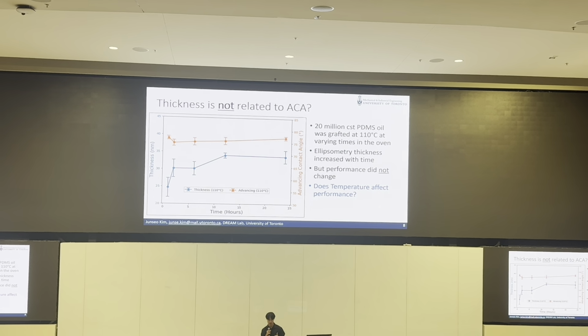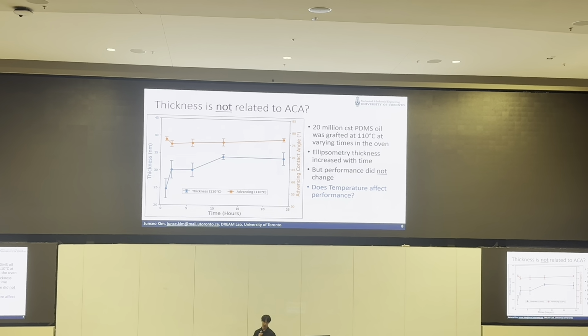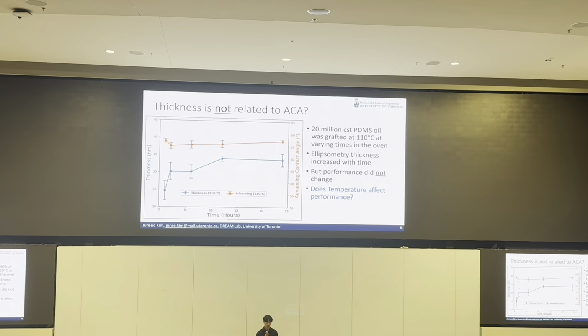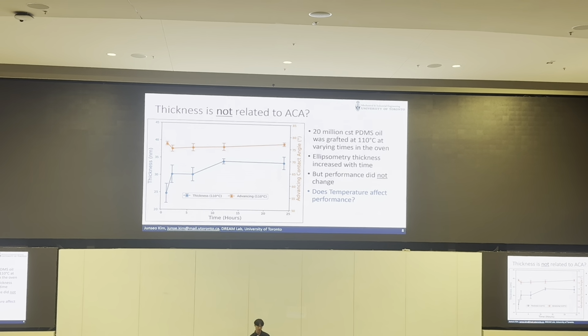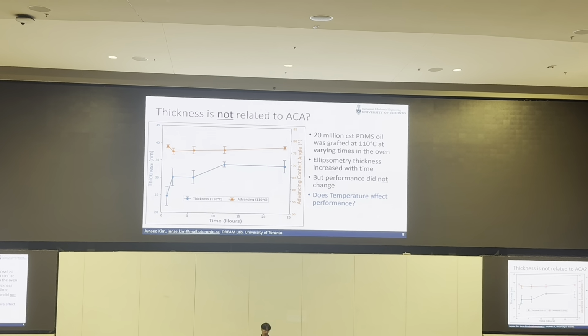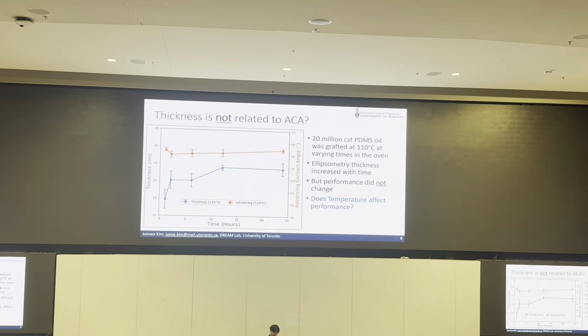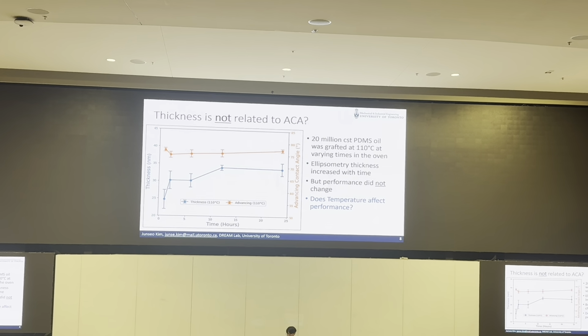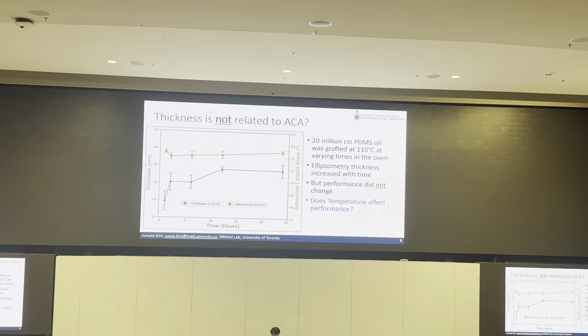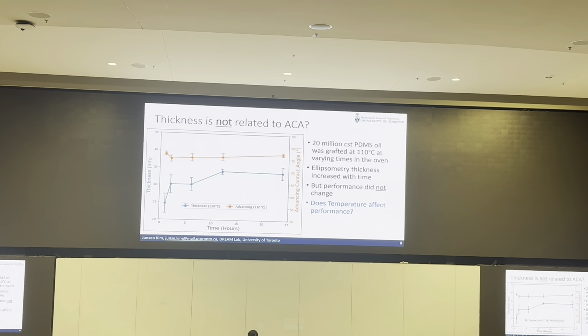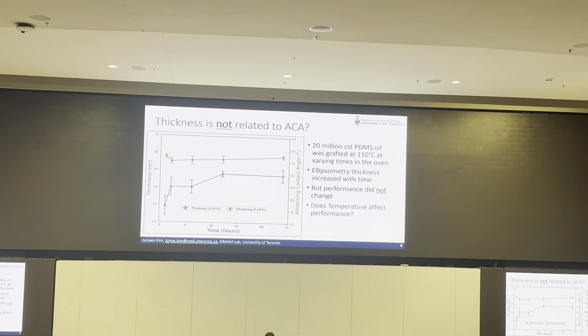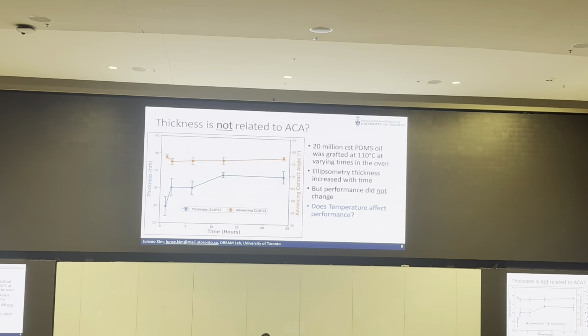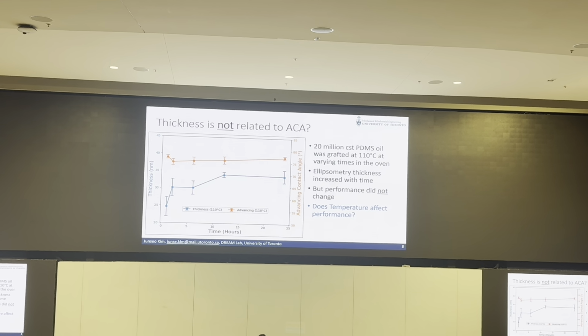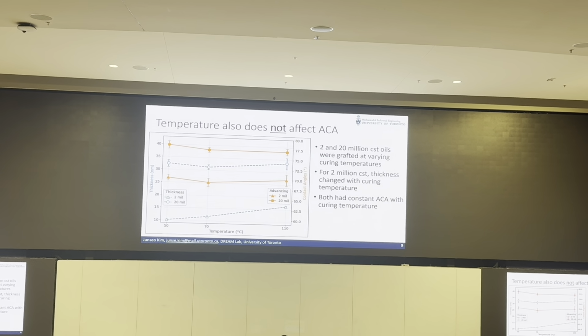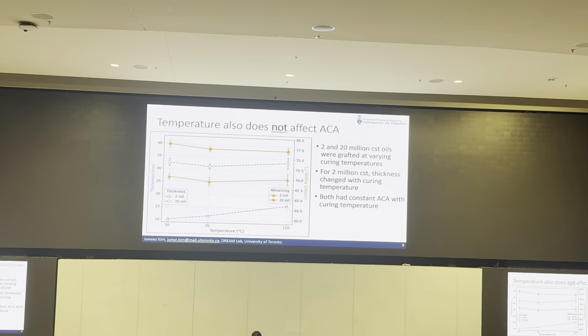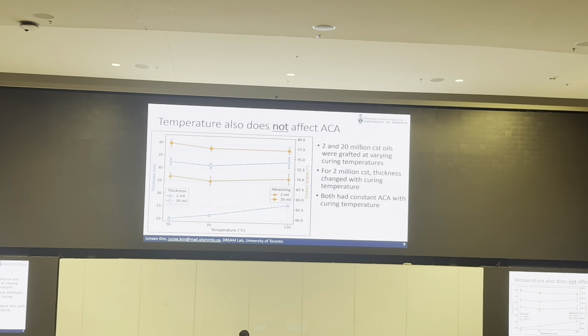You can see that thickness in blue increases with curing time to a certain degree, but plateaus at a time that's typically found around 12 to 15 hours. However, you can see that advancing contact angle remains constant, generally around 75 degrees like I mentioned. So this got me thinking, if thickness doesn't relate to advancing contact angle, which is our measure of performance, then what does? Does the curing temperature affect it? And so I checked that. Temperature also doesn't affect advancing contact angle.